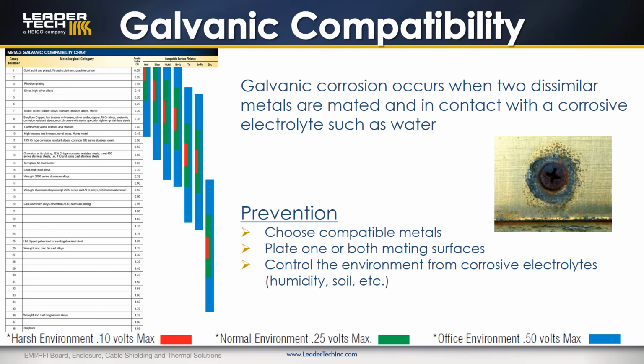The chart shown here lists 38 groups of metal with an anodic index voltage. For harsh environments like outdoors or high humidity, it is recommended that the difference between the metals not be more than 0.1 volts maximum. For example, nickel is 0.3 volts and beryllium copper is 0.35 volts. Their difference is 0.05. These metals are very compatible.